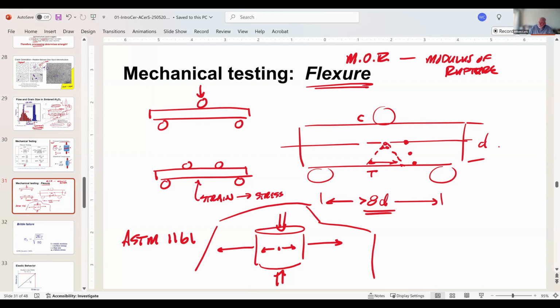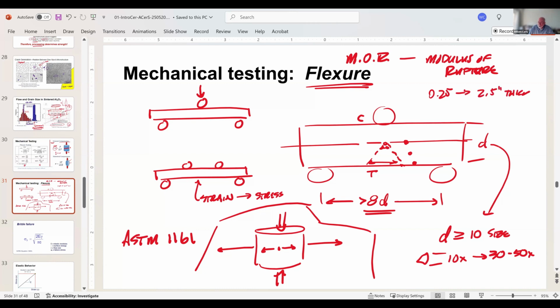This 8 over D thing also applies. D should be a minimum of at least greater than or equal to 10 times the largest feature size. Meaning that if I have an aggregate in the system, my D has to be at least 10x this value. Even better, it should be 30 to 50x. For example, in a concrete specimen, let's say I had a 1/4 inch feature, 0.25. That means my specimen now has to be 2.5 inches thick, right? And if I do 8 times 2.5, I end up with 20 inches as my span, L.